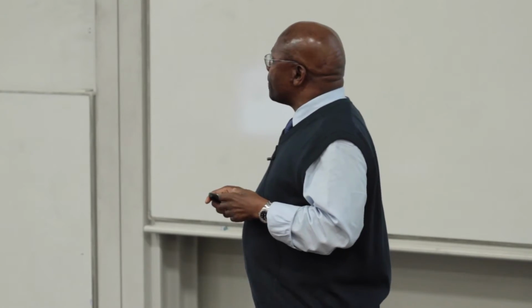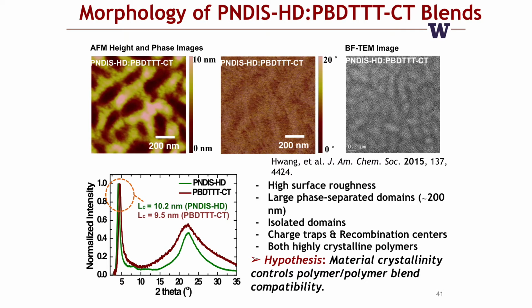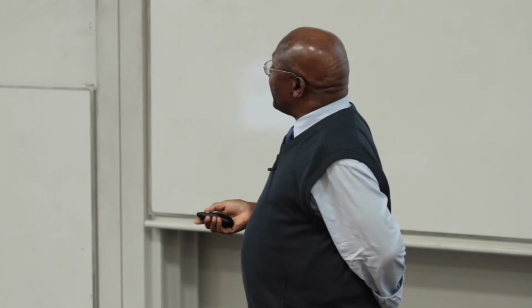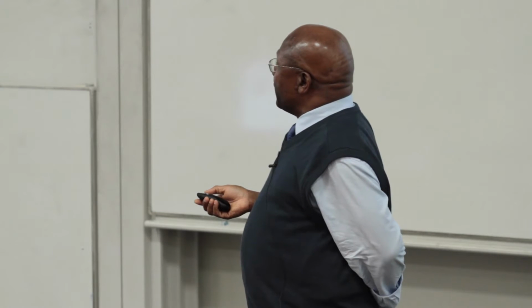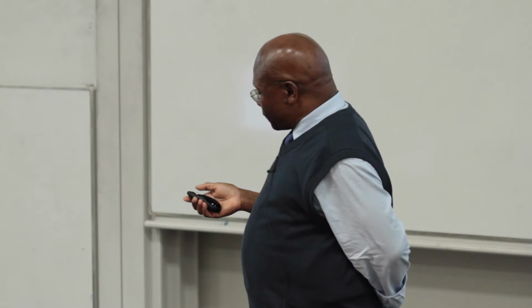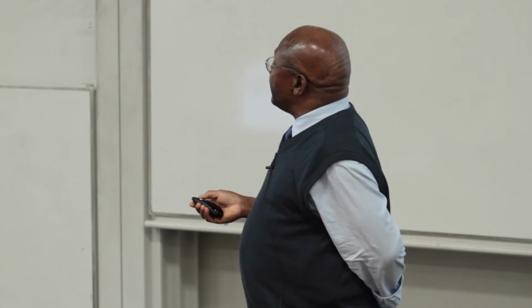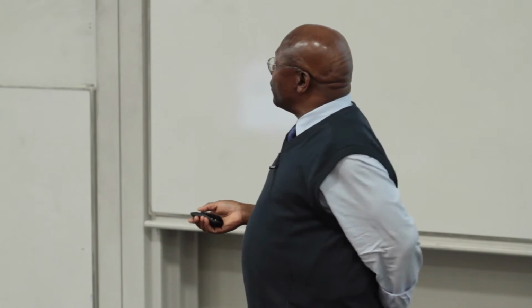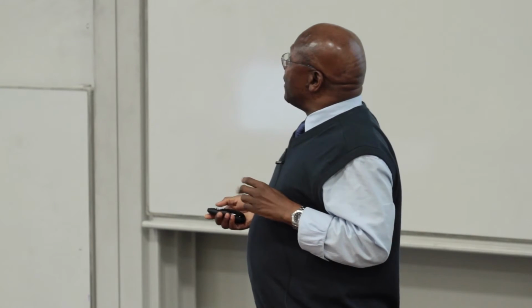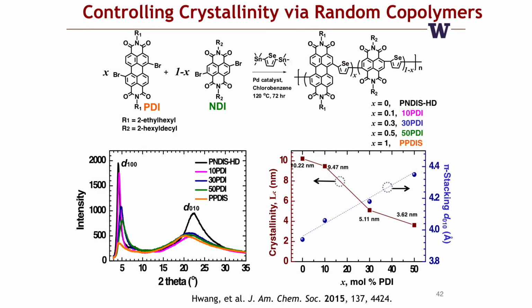So we looked at the morphology and discovered that in this blend system, it tends to phase separate on a relatively large scale. No matter how we tried to control that, we never could really get them down to domain sizes in a nanoscale range. And we thought that the reason for this is likely due to the fact that the two components, the acceptor and the donor polymer, are both highly crystalline materials. So we decided, all right, let's try and change the crystallinity of the acceptor material by making random copolymers, such as this shown here.